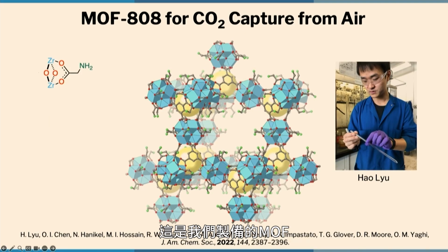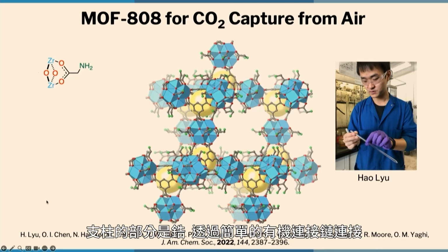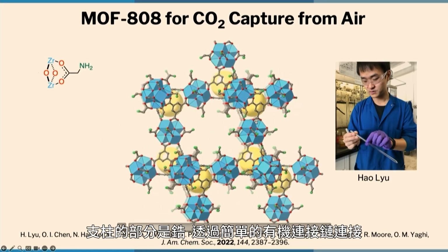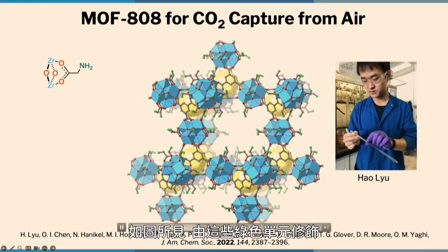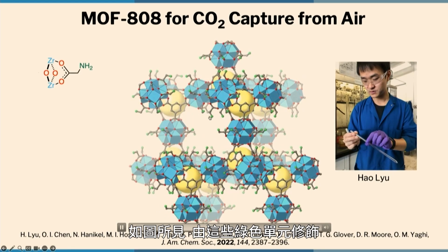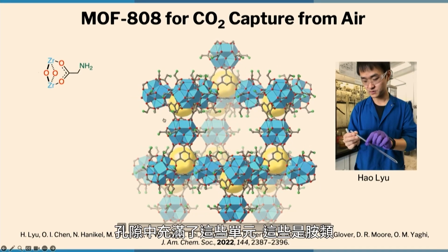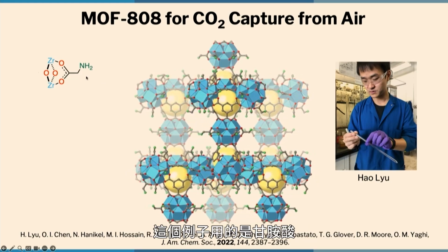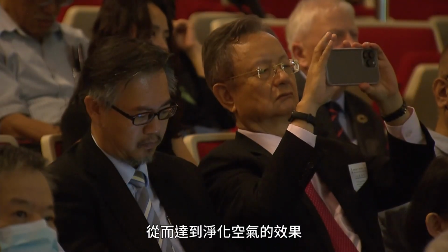And so here's a MOF that we made. It's an amazing MOF, okay? It's made from zirconium hubs linked by a simple organic linker, and it's decorated, as you see here, with these green units. The pores are replete with these units, which are amines, in this case glycine. This amine is placed there intentionally, and it would be the molecule that will extract specifically CO2 from air, because CO2 reacts with this amine. Because the structure has open pores, the CO2 can go into the pore and attach itself to the amine, and thereby you've scrubbed the air.